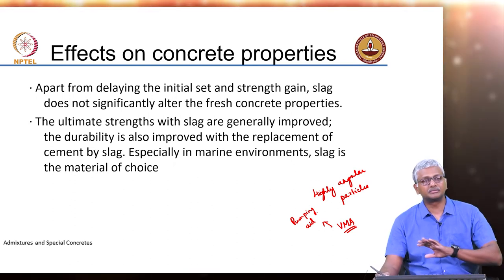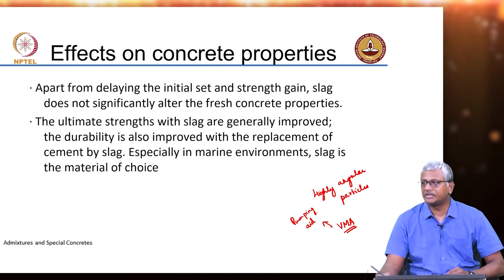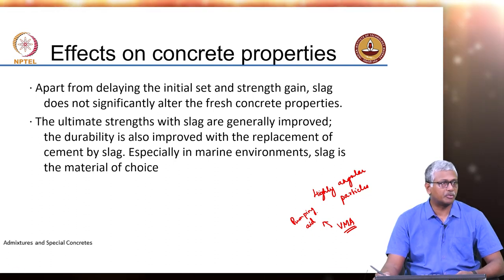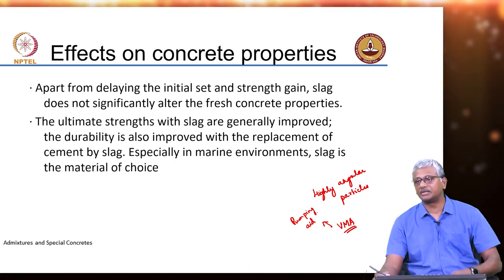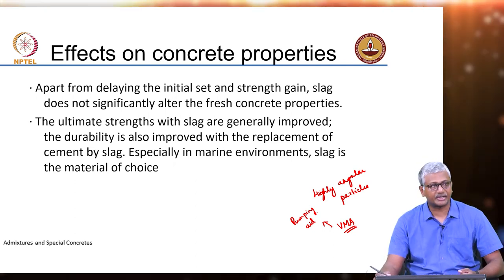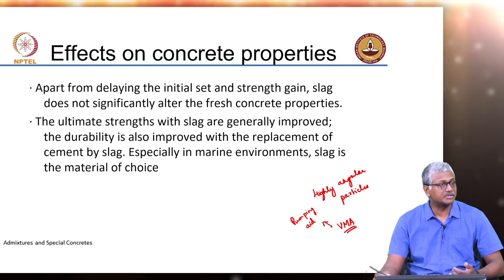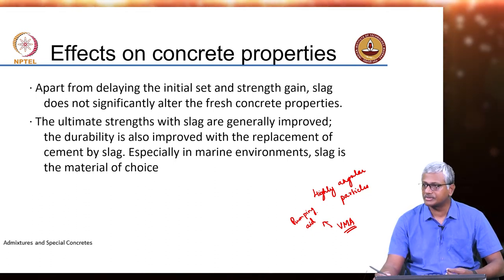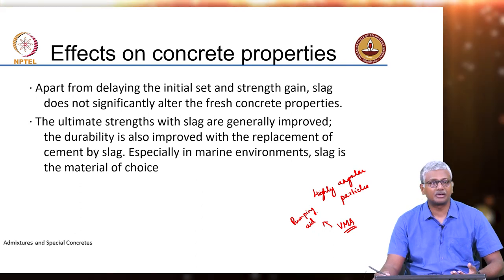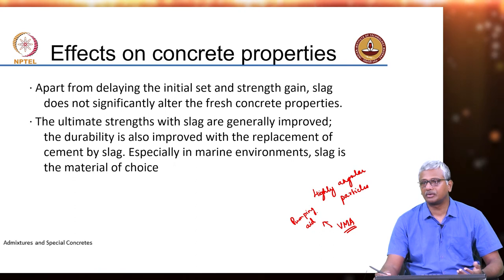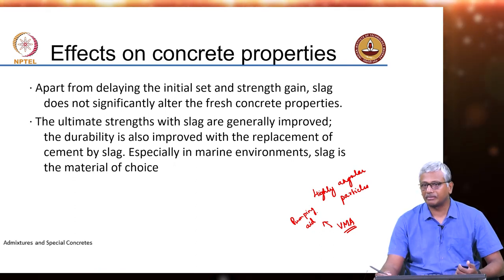Now when you talk about continuous curing, the ultimate strength with slag will generally be improved. And regarding durability, we already talked briefly about that — because of the presence of alumina, there is a large proportion of binding of chlorides that actually happens, and because of this in marine environments, slag concrete is almost always the material of choice. More often than not, people will be using slag concrete in marine environments.